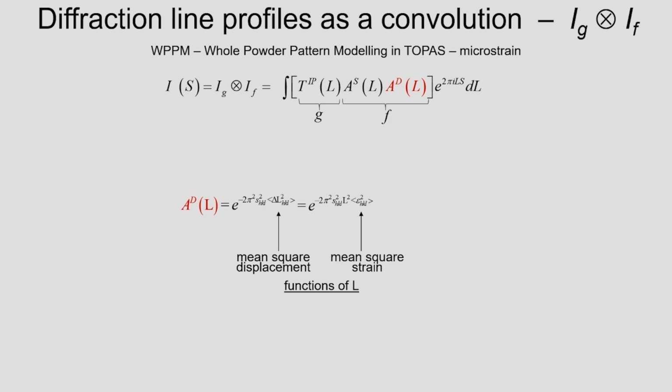And this quantity, which is the mean relative square displacement, we should say relative, because it's the displacement between any 2 points. But now we don't treat this displacement as a constant, because the strain is inhomogeneous. So depending on where you are, this displacement will be different as a function of L, the distance between the 2 points. So it's a complex thing.